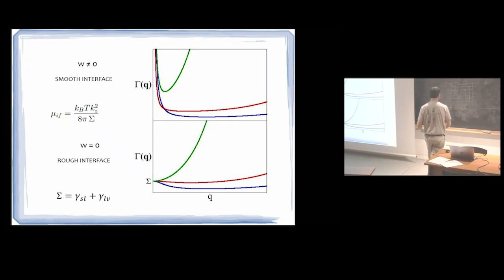So what that says is that when eventually you become fully rough, then your pre-melting film is behaving just like a fluid interface in which these two surfaces fluctuate. They are coupled. In the long distance, they are coupled. And it behaves like a single effective interface with a surface tension that is the sum of both surface tensions. So that makes sense. Okay.